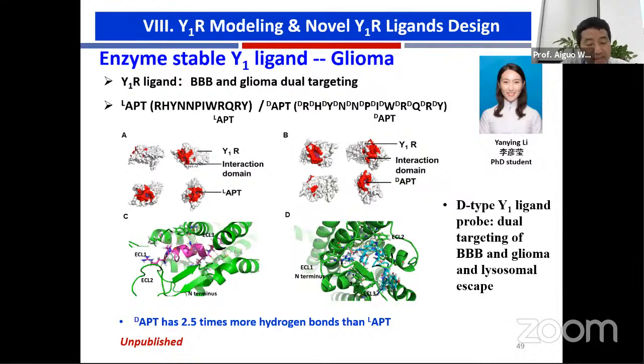For example, after selecting one of six Y1 receptor ligands, we found that they can cross the BBB and with glioma dual-targeting. And also we found a very interesting thing: the L-type APT peptide is different compared to the D peptide. The D-type APT has 2.5 times more hydrogen bonds than the L-APT. And also we found the D-type Y1 ligand probes with dual targeting of BBB and glioma and the lysosomal escape.